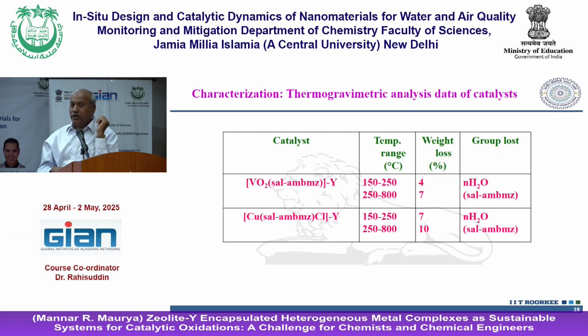All right, so that can give you an idea about the decomposition of ligand, and whatever percent content you are getting is coming due to ligand present in the cavity, if that is perfectly washed and all unreacted ligands or free ligands are removed from the mixture.